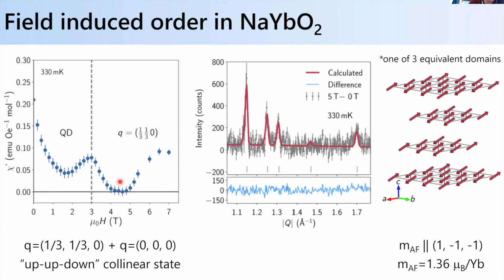Basically around 5 Tesla is where you're in this ordered state. So we can do neutron diffraction under 5 Tesla, okay? And again, this is a powder measurement, so the phase boundaries are not sharp. You can envision it as a powder averaged phase boundary. So we look at the neutron scattering under 5 Tesla, and we do indeed see magnetic peaks show up, consistent with the formation of an ordered state.